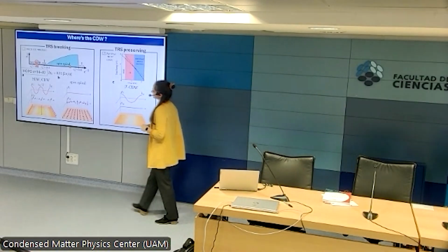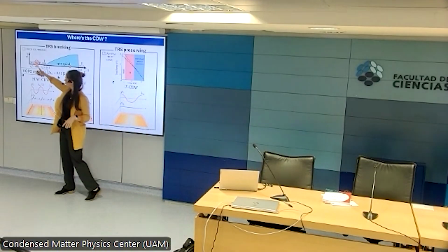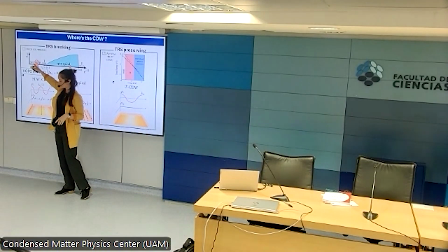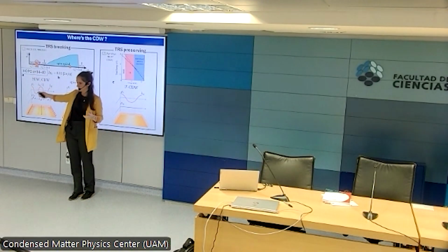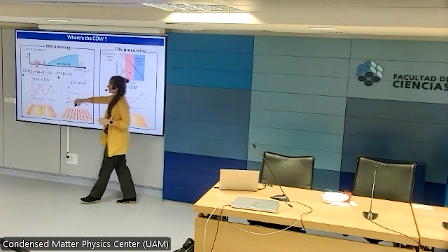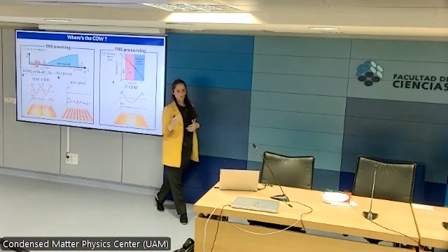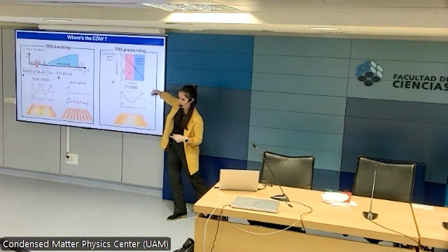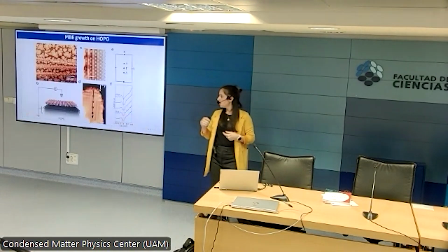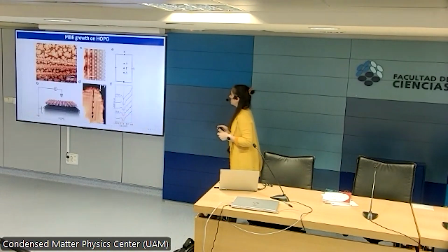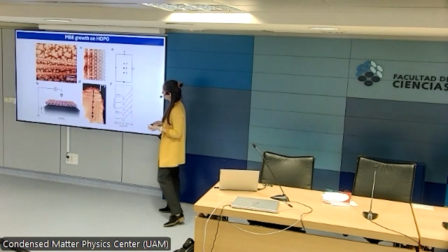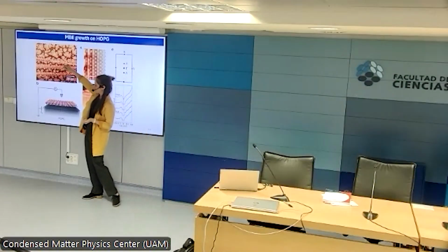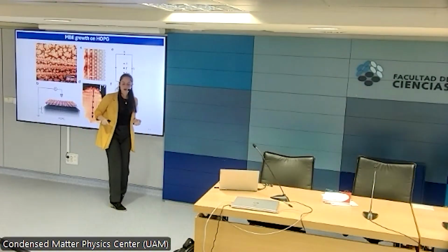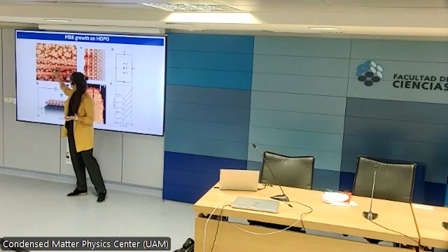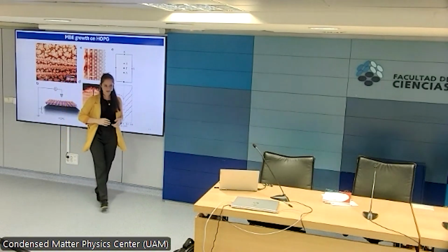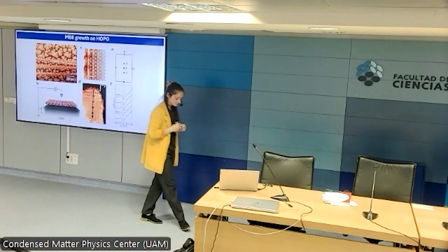To do so, we chose HOPG as a substrate because this would put us here in our phase diagram, which means we would be able to, in theory, spot a charge density wave. And then from the periodicity of the charge density wave, we would know if we were in that case or in this other one. So after a lot of effort, we grew tungsten ditelluride on HOPG. This is your STM image showing you the formation of islands. These bright lines here are just step edges on graphite, and you can see that the nucleation of the island starts from the step edges.